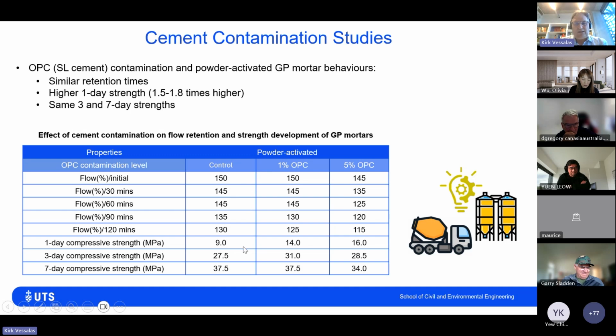And again, our strengths are quite impressive. They're not really impacted by the presence of the Portland cement in the system. So again, we get similar retention times. We get a higher one-day strength, about 1.5 to 1.8 times higher than the conventional cement systems, the binary and ternary blends, and we get the same 3 and 7 day compressive strengths. So it's pretty impressive technology.